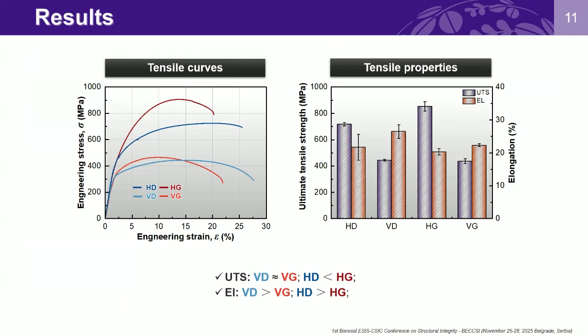To compare the mechanical properties of the directed deposition sample and the gradient deposition sample, a series of tensile tests were carried out along the horizontal and vertical directions. As a result, in the vertical direction, the strength of the gradient deposition sample is similar to the directed deposition sample, but the elongation is relatively lower. In the horizontal direction, the gradient deposition sample exhibits significantly higher strength than the directed deposition sample, while its elongation is relatively lower.